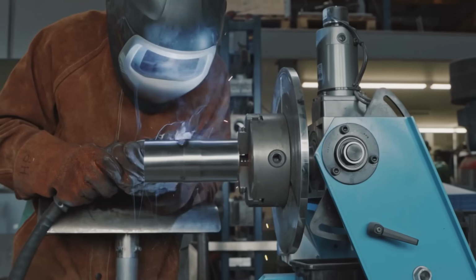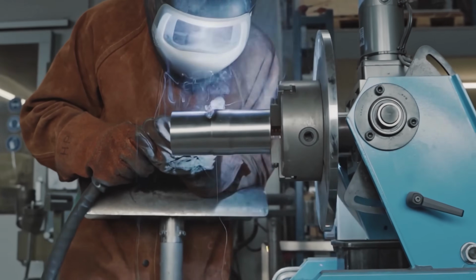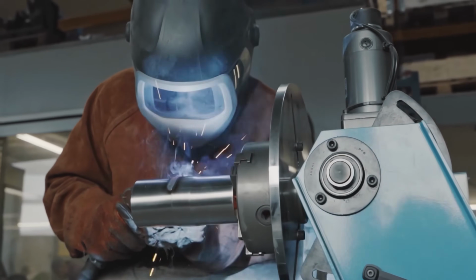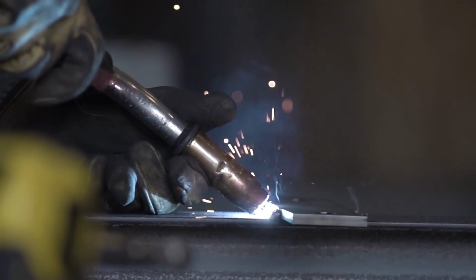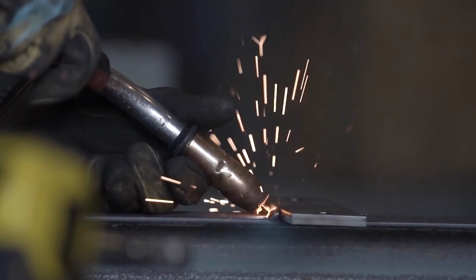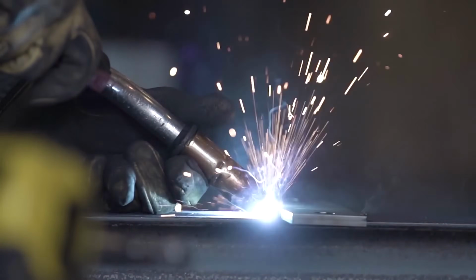In weld beads of austenitic steels, it's common to have a fraction of delta ferrite in the weld metal to reduce susceptibility to solidification cracking. This ferrite is ferromagnetic, so a magnet can stick to the weld bead area or the heat-affected zone, even if the main body of the material is mostly austenitic and non-magnetic. Again, this doesn't indicate counterfeiting, it just shows the presence of a magnetic phase locally due to the welding design.